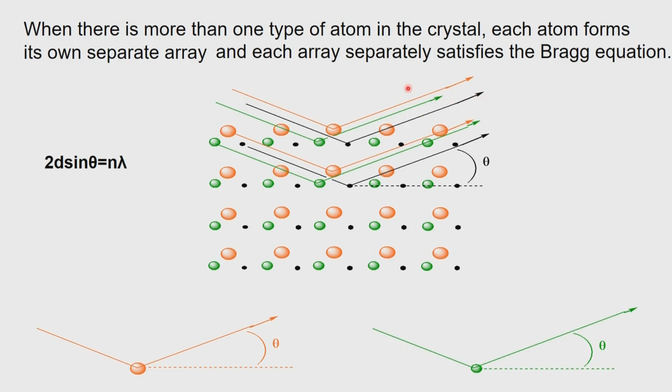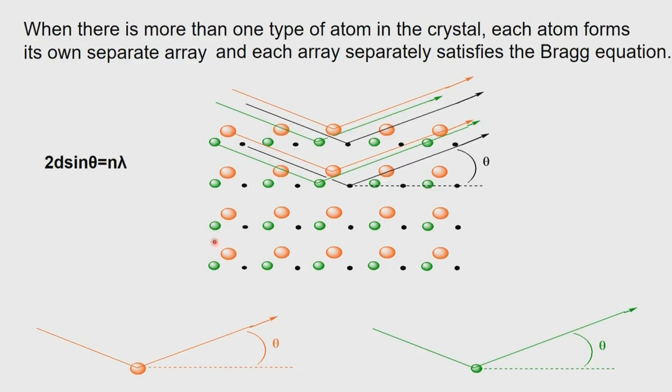So, when we measure the intensity from the plane, we have a collective measure of all these atoms scattering at that particular theta value. Obviously, the intensity will depend upon where these atoms are located, and that is the main issue. We have to find out where these atoms are located. But the fact that we are getting it from the various planes, which we can locate by Bragg's law or for that matter the Laue condition, tells us that it is in principle possible to find where these atoms are, depending upon the intensity now.